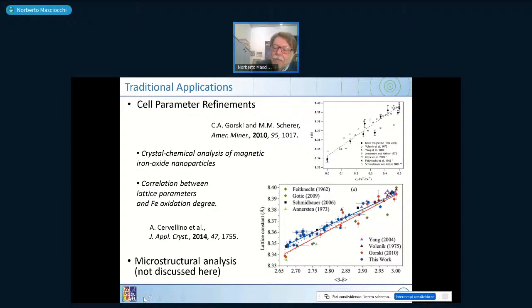So some years ago, we decided to prepare nanoparticles with 30 different methods, and these are the 30 blue dots there, compared to all the other colors and shapes, which are from different workers. You can see that if you add all the data together, you can make a straight line, which is the red one. But if you take only those that were prepared deliberately and measured with synchrotron radiation, these are the blue ones, then you have a straight line, which is still very good and even better, and is slightly shifted away. So you can have a very accurate determination by just measuring the lattice constant, and the calibration line is different, so you get different results from a good calibration.